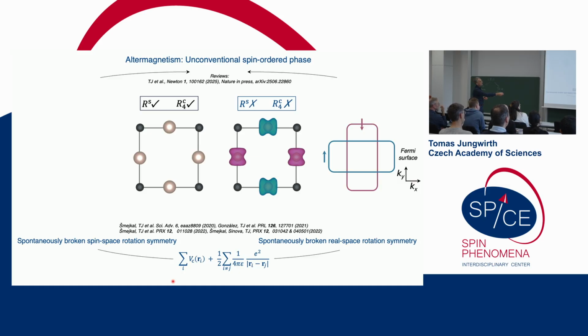But when you look at the ordered phase here, you see that first of all we now have the spin polarization. That means that the spin space rotation symmetry is broken. But also what you see here is now you cannot anymore rotate your crystal by 90 degrees because you would end up in a different state. So you also break the real space fourfold rotation symmetry. But what is very important in altermagnets is that there is a retained symmetry. There is still one symmetry which was already present in the non-magnetic phase that persists also in the ordered phase.